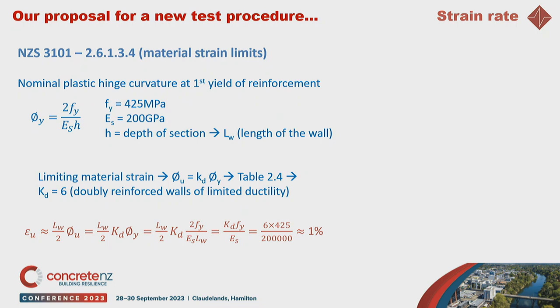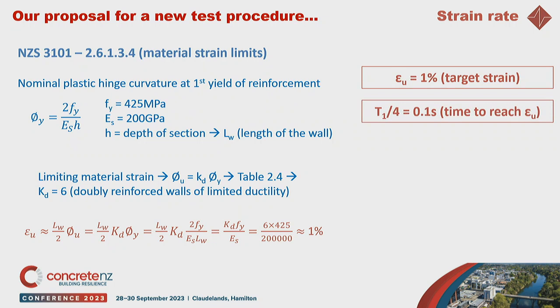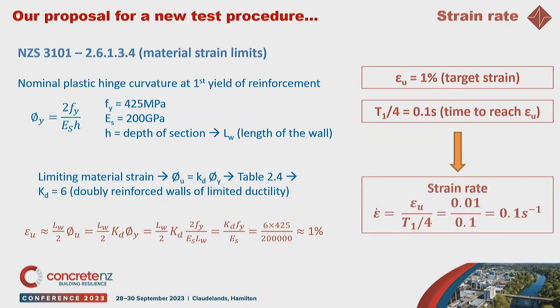I'd like to point out that if we started with a more ductile structure, of course, epsilon u would be double, like 2%. But at the same time, the time would also be longer. So in the end, I end up with the same result. For the moment, we have epsilon u as a target strain, and T1 over 4 is 0.1. Therefore, the strain rate would be 0.1 seconds to the power minus 1.